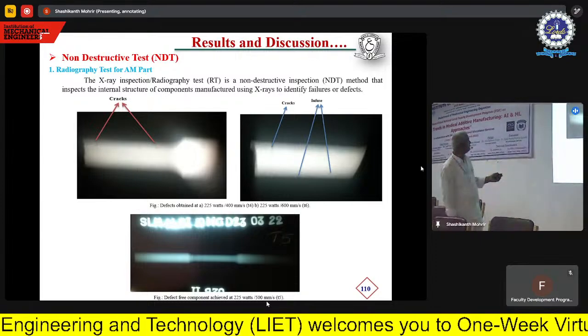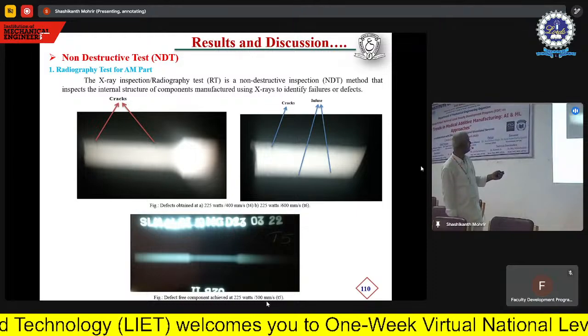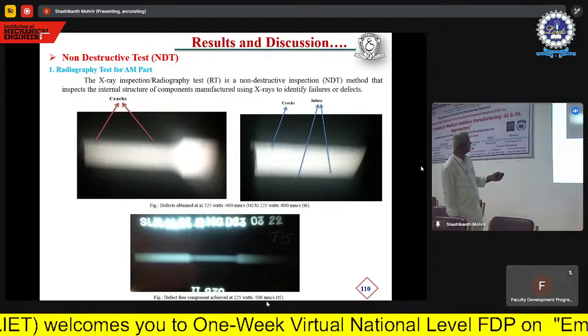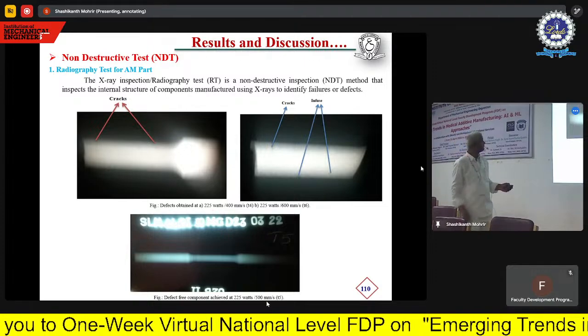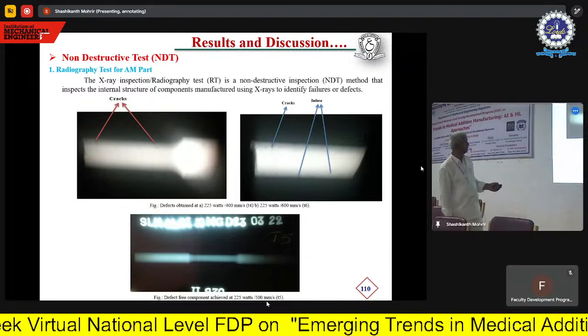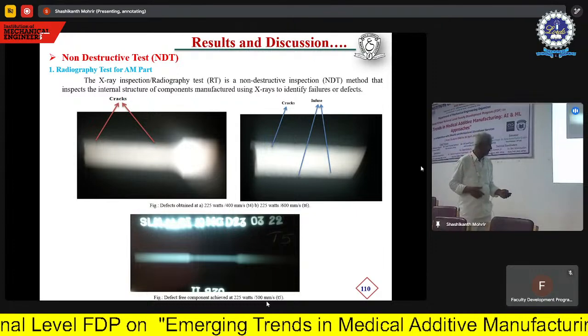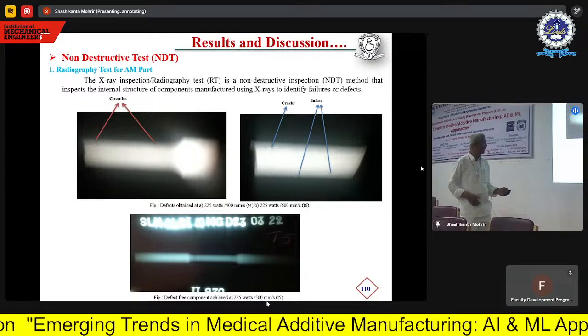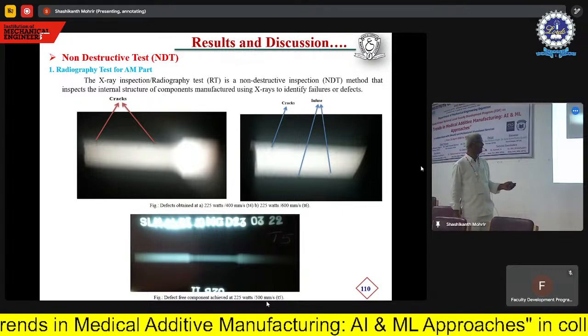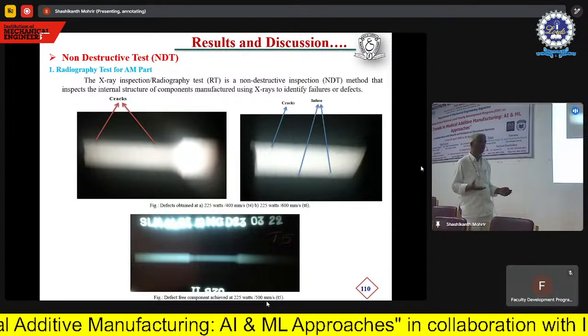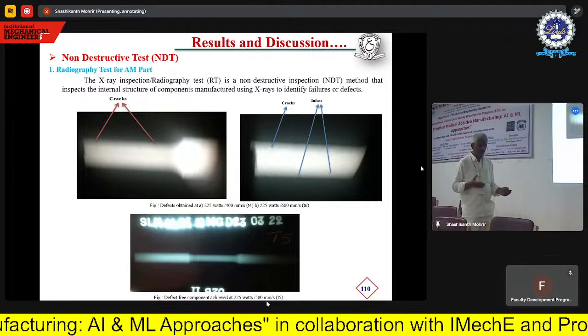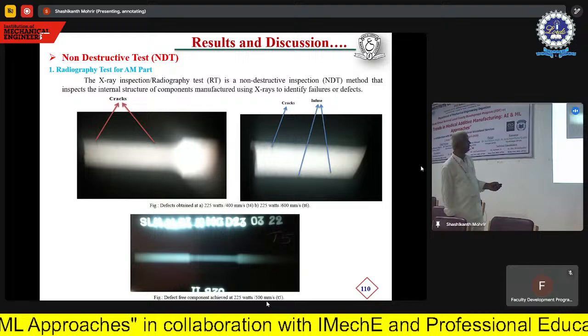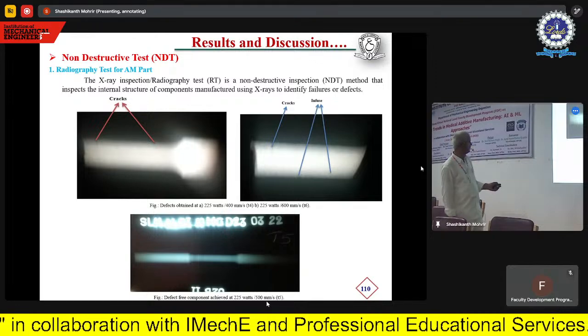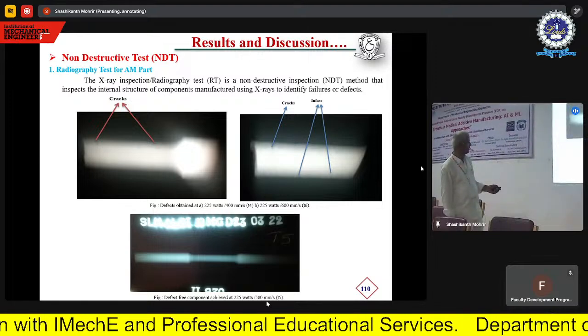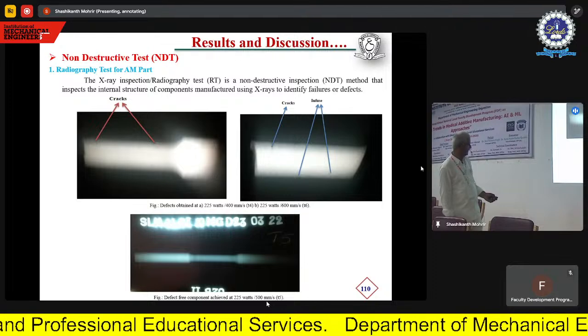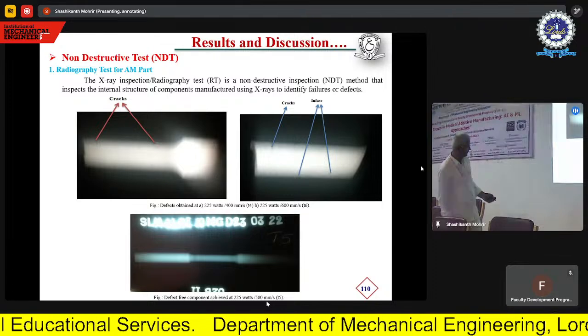So the cracks are not visible, but my scholar identified 2 cracks here. And this information is given by the NDT inspector, indicating that. So the picture is not showing any cracks. So this is the interpretation by the NDT radiography inspector, who identifies as an expert and indicates the error. So what is it? Defects obtained at 225 watts, 400, 225 watts, 600. Achieved for sample T5. This is for T5. Okay.